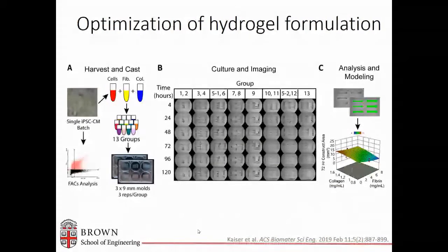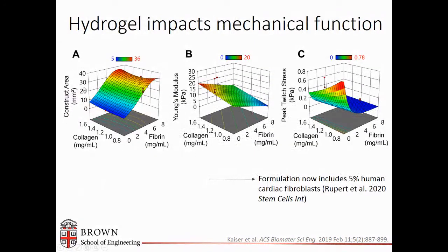What we've done is look at fibrin and collagen as two hydrogel sources that are commonly used in the field and highly compatible with the iPS-derived cardiomyocytes. We used a design of experiments approach and came up with 13 groups where we could, over 5 days, take images to look at compaction and culturing across all of these groups. We did our analysis and response surface modeling, and what we found was that a more compact tissue is going to create a more uniform syncytium and uniform beating.